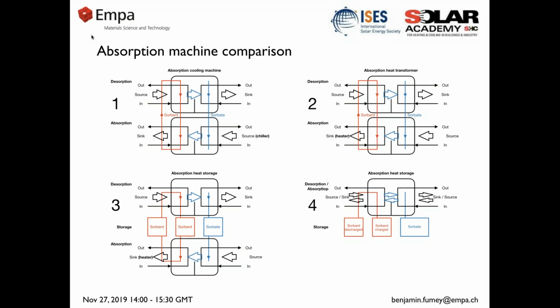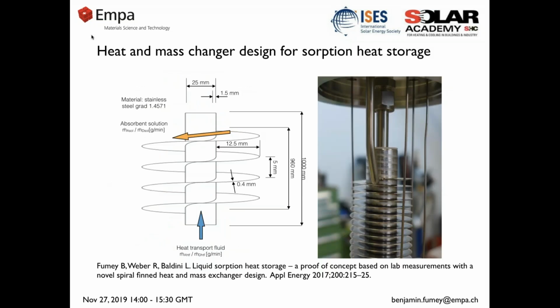For this reason, we find for the liquid sorbents, the tube bundle falling film heat and mass exchanger as used for chillers and for heat pumps is not ideal. So we've gone towards developing a spiral finned tube heat and mass exchanger, also reported in the below publication. And one of the main things that we reach here is a much longer exposure time of the sorbent, which is needed to be able to move towards that equilibrium line to get those high energy densities.